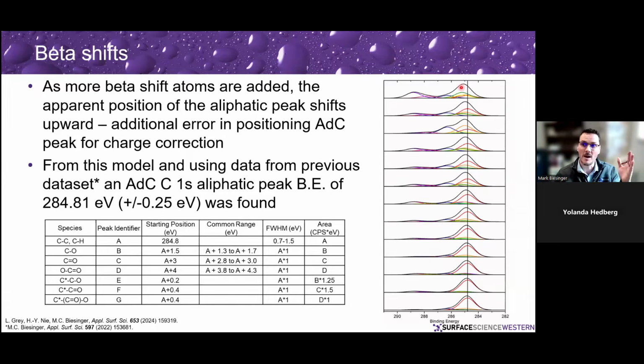And so that's a lot of error that you're adding if you just use a peak maximum or your standard curve fitting, compared to including these beta shift effects. When we did that, using data from the previous model, we found that the aliphatic peak was at 284.8 eV plus or minus 0.25 eV. And so that 284.8 binding energy for that alkane peak, which has been suggested by others in the past from looking at just alkanes and things like that, is again what we want to be using for adventitious carbon, I think.